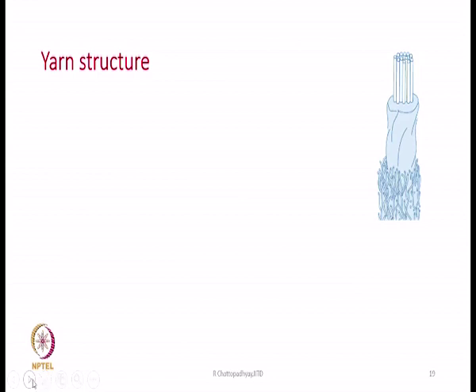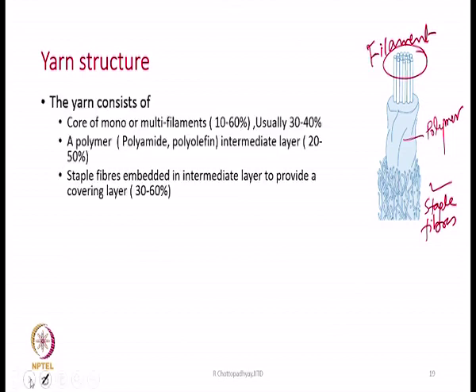The yarn structure is shown here. Typically, you have filaments, then this is the polymer, and you have staple fibers. So, typically it will look like this. It consists of a core of mono or multifilament, 10 to 60%, but usually it is 30 to 40%. A polymer, which could be polyamide or polyolefin, as an intermediate layer, 20 to 50%, and staple fibers, which could be between 30 to 60%.